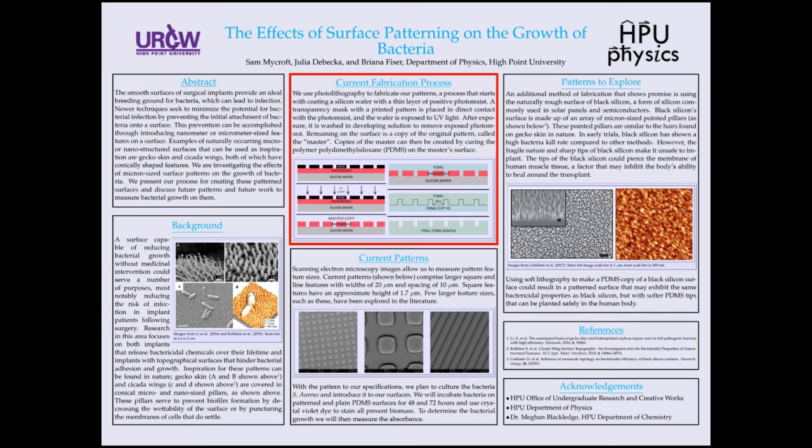We then needed a method to create copies of this master to ensure our pattern had transferred correctly. To do this, the sample is first coated in trichlorosilane, or TCS, an anti-adhesive that prevents our sample sticking during the following steps. Polydimethylsiloxane, or PDMS, a liquid elastomer, is then poured onto the master and baked in order to solidify into a negative mold of our sample.